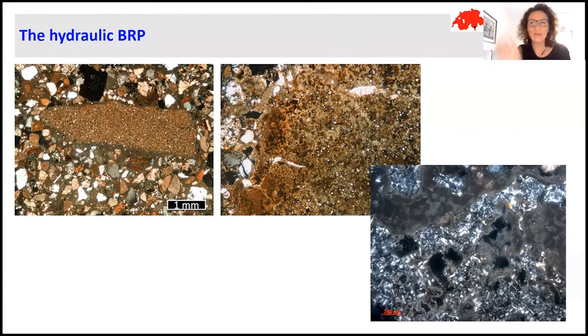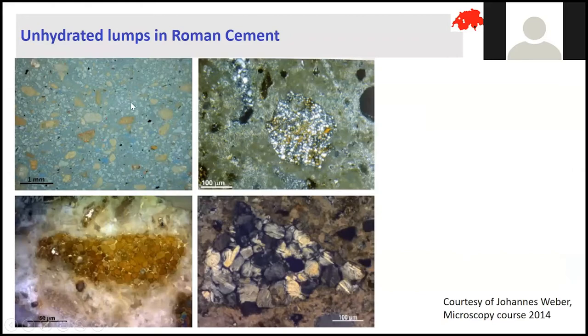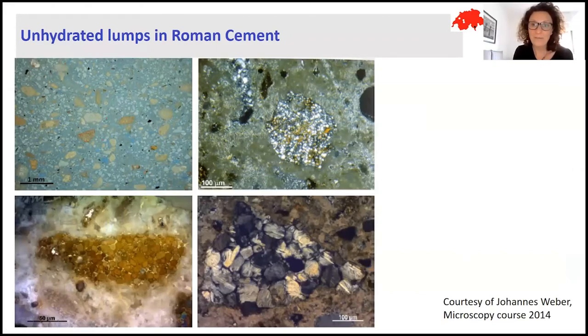If I see some binder-related particles with hydraulic properties, so impure limestone, so a high content of clay, I can infer that probably the binder will be hydraulic. Normally, also in the very first phases of production of cement, as for example the Roman cement, which is a natural cement produced from a raw material with a high content of clay, because of the old process of production, I will have some residues of these clinkers within the mortar matrix. By analyzing the minerals within it, I can say if this is an old cement, a natural cement, or a Portland cement.